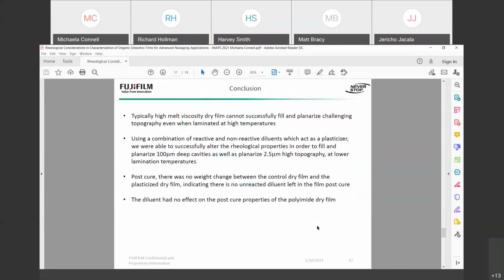So in conclusion, typically high melt viscosity dry film cannot successfully fill and planarize challenging topography, even when laminated at high temperatures. Using a combination of reactive and non-reactive diluents, which act as a plasticizer, we were able to successfully alter the rheological properties in order to fill and planarize 100 micron deep cavities, as well as planarize 2.5 micron high topography at lower lamination temperatures.